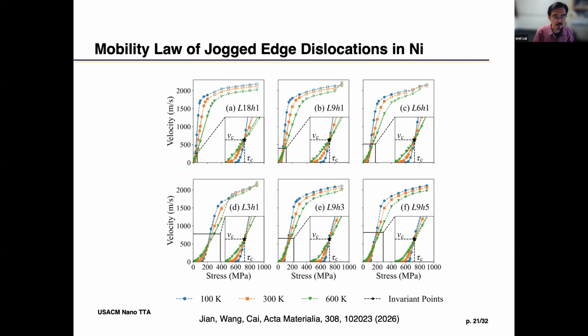Now, in terms of the transition, each data point is one molecular dynamics simulation, right? It's for some configuration, like how long it is, how high the jog is, but each one is different. Different colors correspond to different temperatures, and the horizontal axis is the stress. So this is basically saying that at low stress, you have one kind of temperature effect, and at high stress, you have a different kind of temperature effect. It is consistent with what the textbook says, but it's a little bit too consistent, okay? Basically the jog obstructs your circular motion, right? So you may have a critical stress to overcome that obstruction, but if you're below that stress, you can still move because thermal activation can help you overcome it.